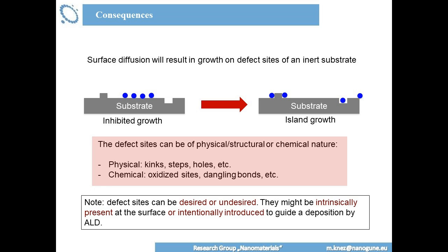Now, the point is that this is happening, for example, if you have carbon nanotubes, if you have graphene, if you have such materials which don't have oxidized functional sites, so you have just a bare carbon surface without any functional group or any kind of dangling bonds, edge sites, and so on. And normally on such surfaces you would not like to have a parasitic growth somewhere. But sometimes you want to have it. So you can have those growth spots desired or undesired.